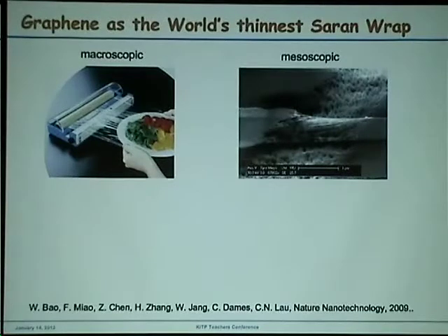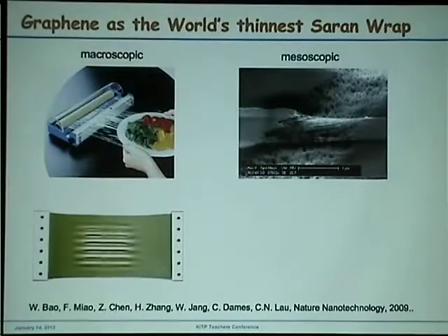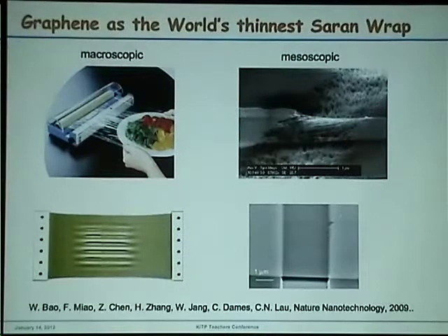This is actually a really ugly graphene device, and because the trench is really ugly, it's just a bad sample. But you can see irregular ripples form because it's pinned by these rugged edges. If you can pin everything and stretch it, then this is what you have for the single atomic layer version. After this, we never look at Saran wrap in the same way in the kitchen.